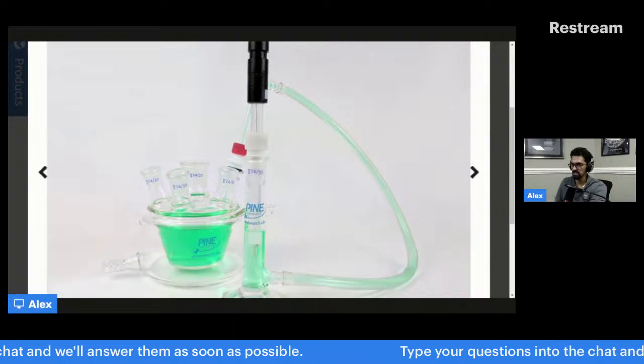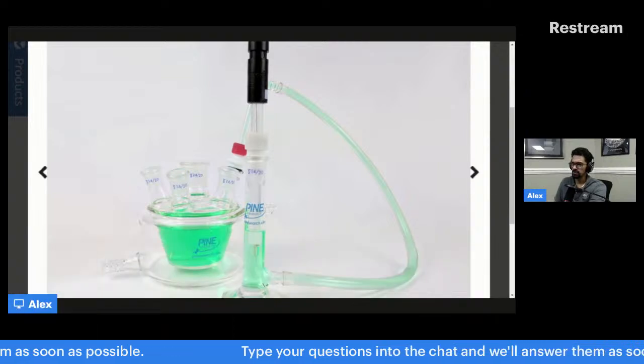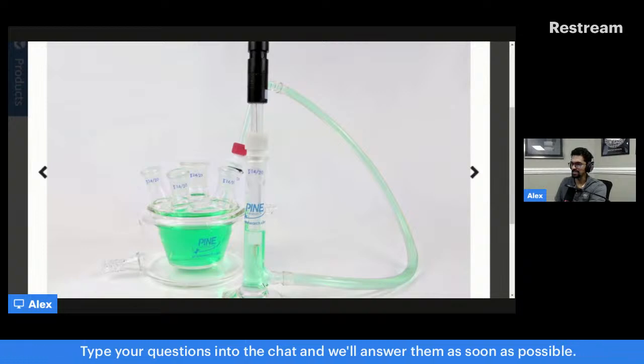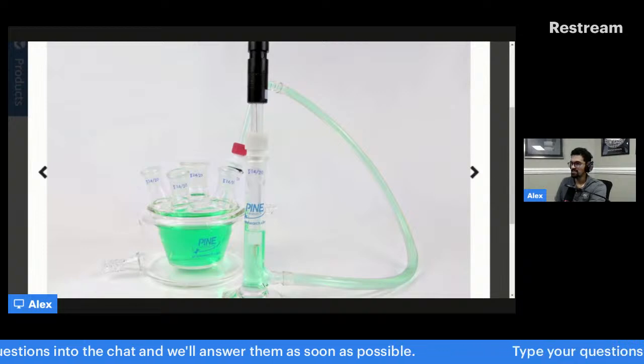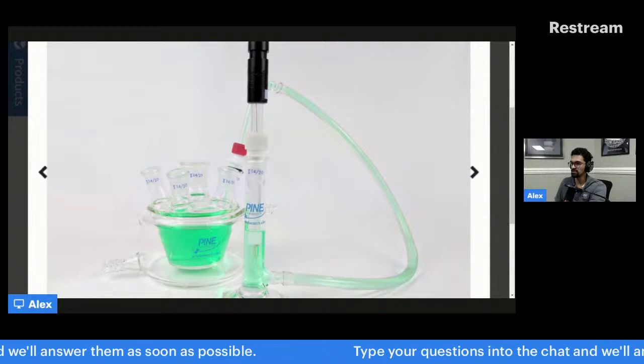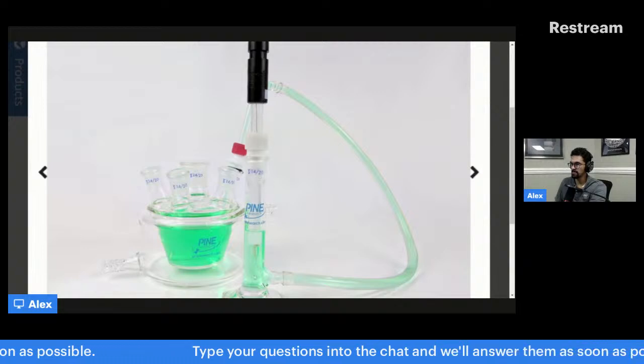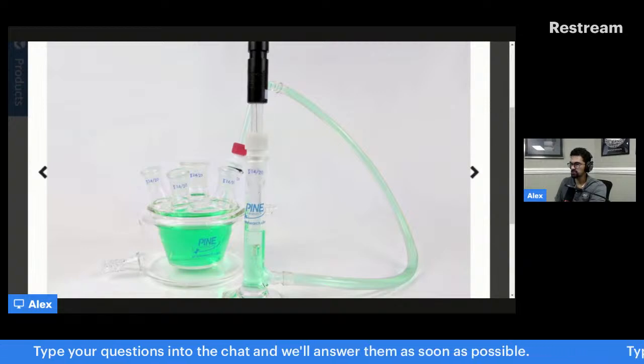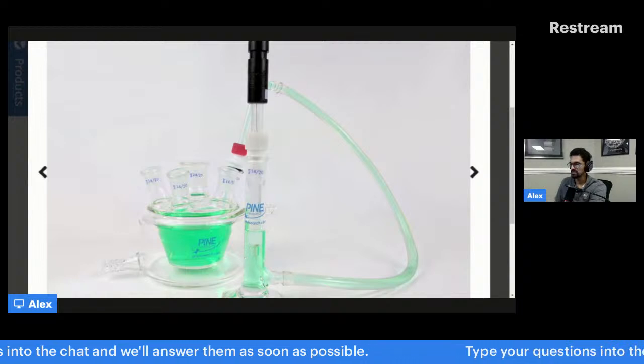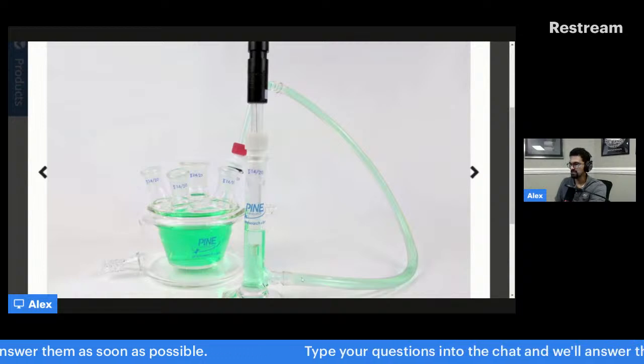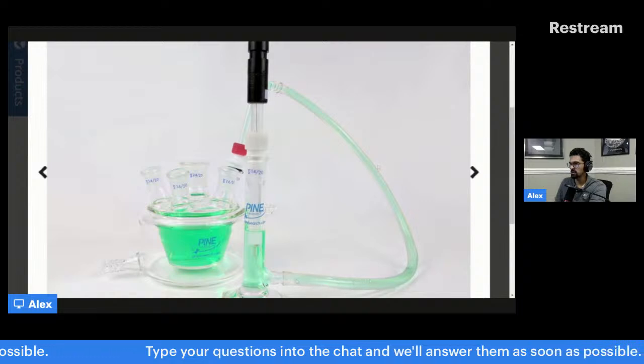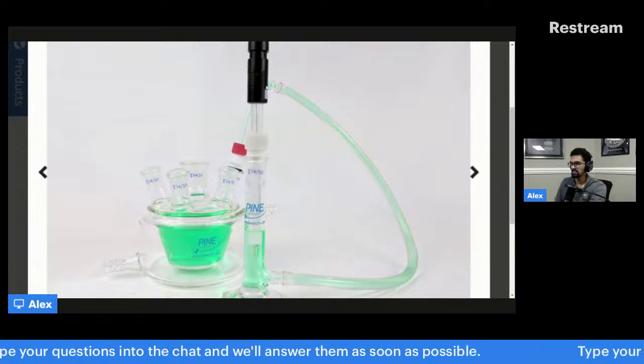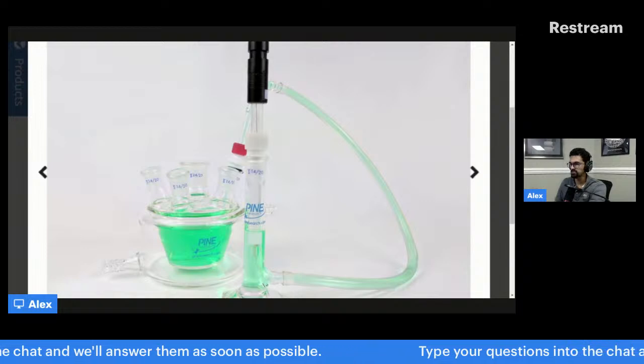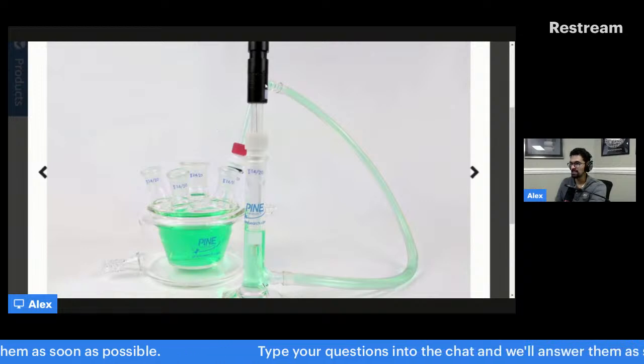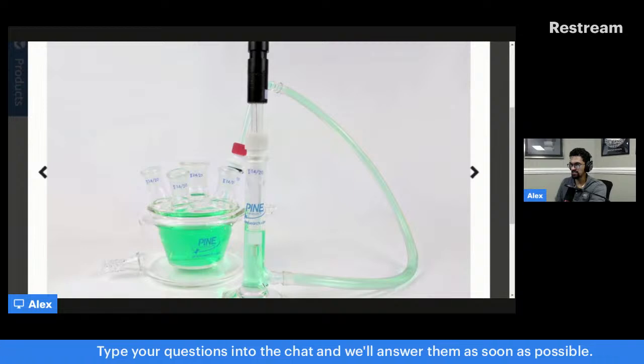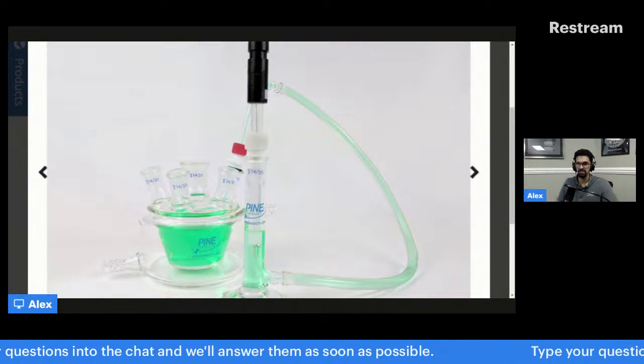So this is a salt bridge kit, and basically you have your electrochemical cell. It's the green cell, and then you have this long tube. Your reference electrode is this guy, and the reference electrode is put into a tube. Basically, it's a graduated cylinder that has a barbed fitting at the end, and then you have a huge length of Tygon tubing all the way to another glass tube, and because you're working in KOH, you may choose a different material, not glass. And then this goes into your cell, and there's actually a frit, not all that different from the reference electrode frit.